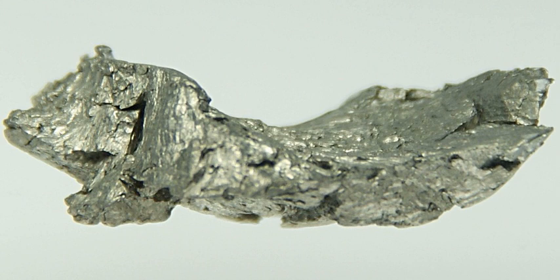Gadolinium as a phosphor is also used in other imaging. In X-ray systems, gadolinium is contained in the phosphor layer, suspended in a polymer matrix at the detector. Terbium-doped gadolinium oxysulfide (Gd2O2S:Tb) at the phosphor layer converts the X-rays released from the source into light. This material emits green light at 540 nanometers due to the presence of Tb3+, which is very useful for enhancing the imaging quality. The energy conversion of Gd is up to 20%, which means that 1/5 of the X-ray energy striking the phosphor layer can be converted into visible photons.